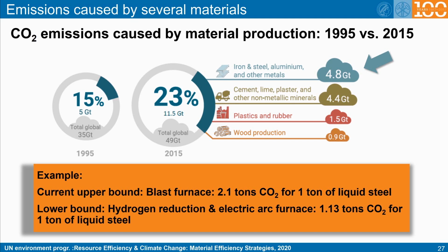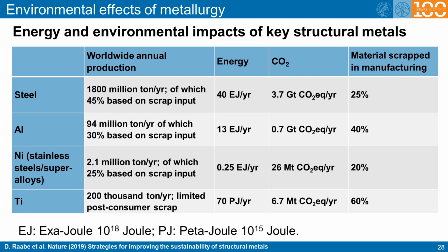In the case that the iron ore production is done exclusively by hydrogen, and that the so produced iron sponge is thereafter melted in an electric arc furnace, leaves us with about 1.1 tons of CO2 for 1 ton of liquid steel. This can be seen as a lower bound for steel production during the next decade. Further reduction of the CO2 balance could be achieved when only green energy sources were used for operating the electric arc furnaces, and if the huge graphite electrodes that are currently used in these furnaces could be replaced by inert electrode materials.